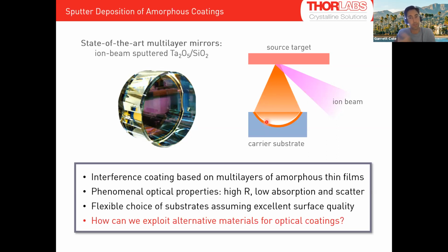If you can get good surface quality on that polished substrate and guarantee good adhesion between the deposited films, you can get excellent surface quality. Angstrom level RMS roughness, which gives you optical scatter at the ppm level, and sub-part per million absorption, just due to the high purity, wide band gap of these metal oxides. So it's a flexible technique in terms of the substrate material choice, or even topography or figure of that substrate. It's scalable in terms of manufacturing. As long as you have good uniformity in the chamber, you can load a number of substrates.